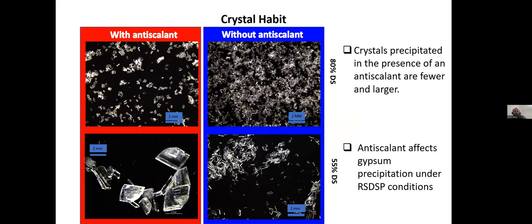I also separated the crystals from solution at the end of the experiments where I had nucleation plus growth. And we see here crystals from two experiments. On the left, with our red background, are crystals that precipitated within brines with scale inhibitors, and on the right, without. The two top ones have the same chemistry. The two bottom ones have the same chemistry.